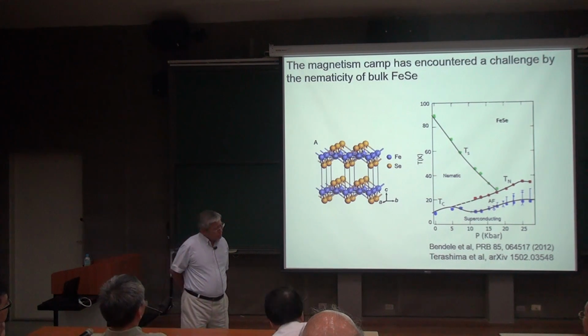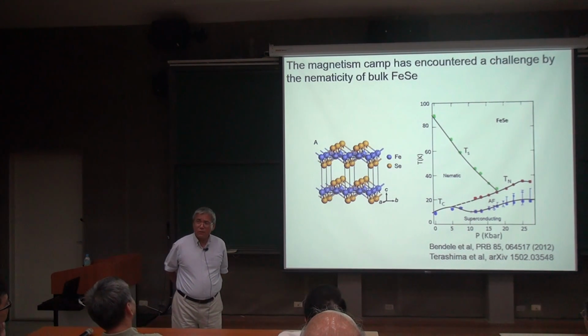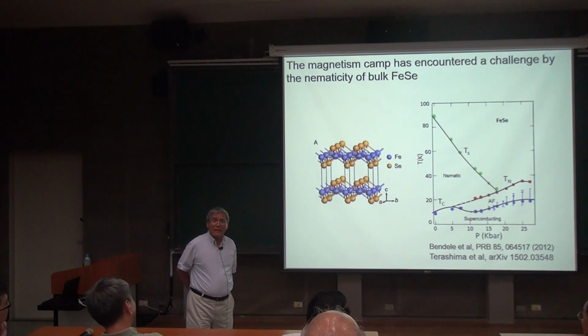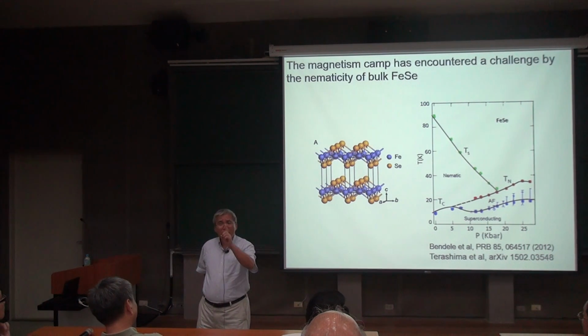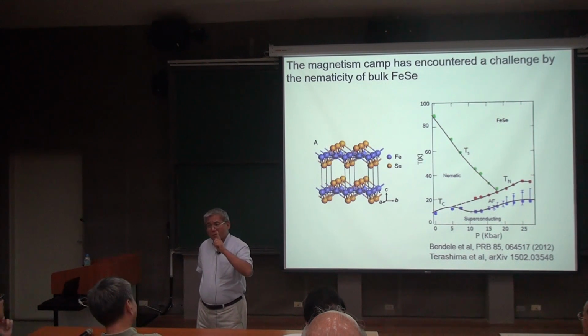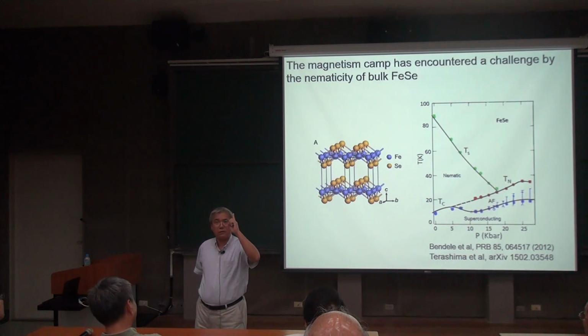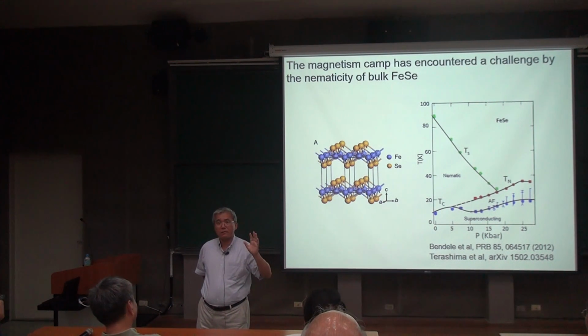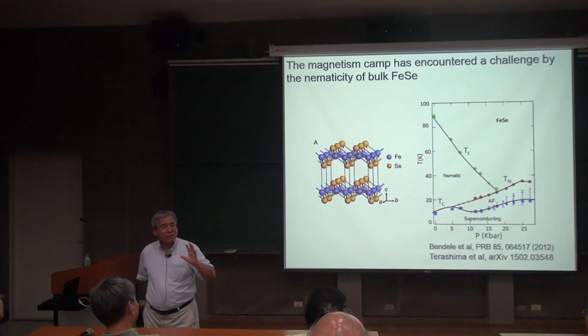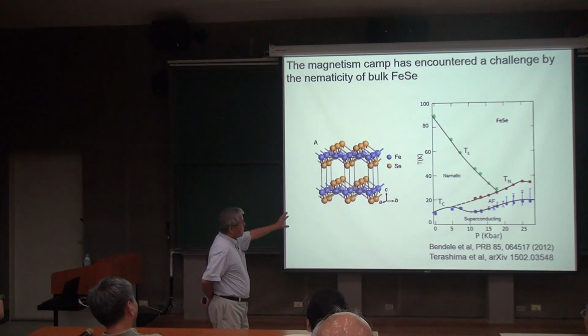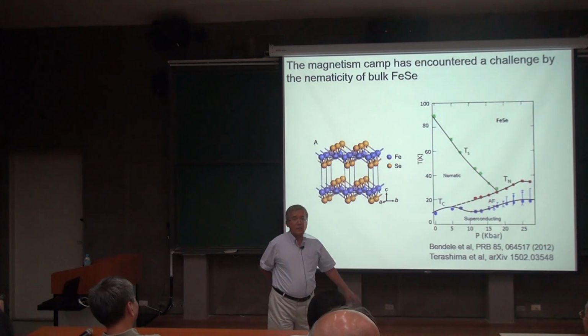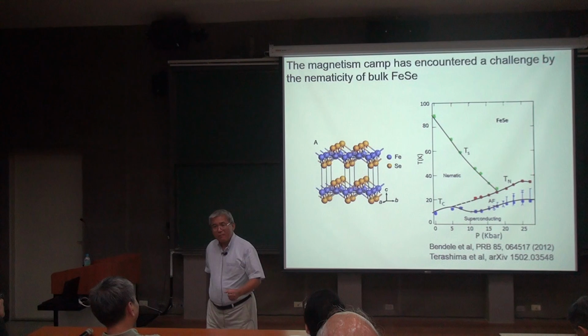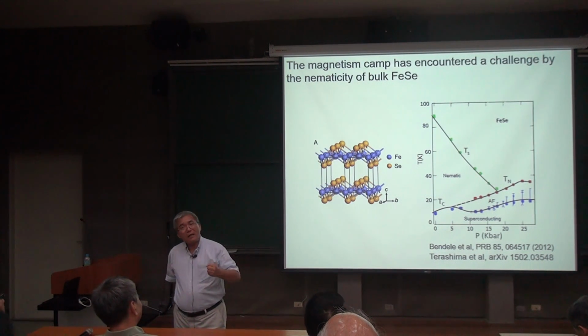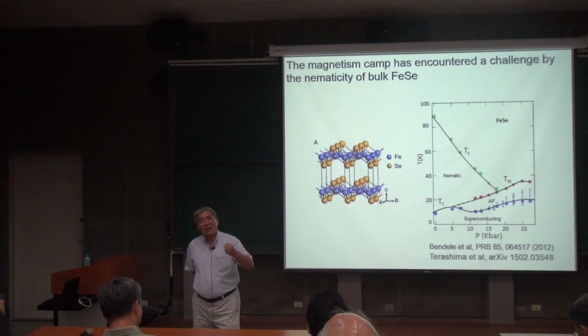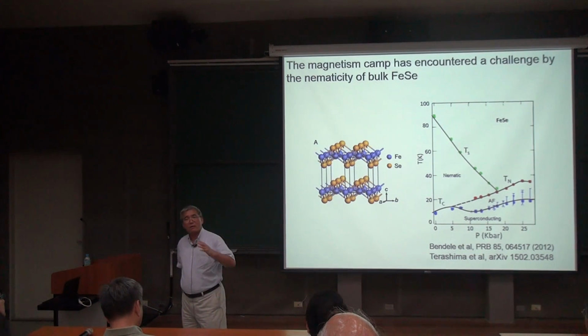You might argue, wait, but this is not fair because it is only one material. For all the other materials, it is not like this. But in science, if you establish one case in which nematicity is caused by orbital fluctuation, that forces you not to ignore the orbital fluctuation for all the compounds. So this becomes, at this moment, the most debated issue in iron-based high-temperature superconductivity, namely what's causing iron selenide to spontaneously distort at such a high temperature and with no magnetic order whatsoever.